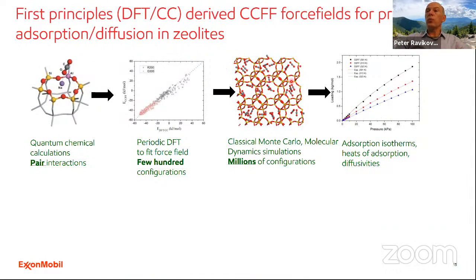As I mentioned before, the quality of the force field is the most important for all the simulations, adsorption or diffusion. One of the approaches we've been taking, in collaboration with the group of David Sholl at Georgia Tech, is to develop force fields based on first principle calculations without resorting to fitting to experimental measurements. In order to do that, we start with DFT calculations, where we perform periodic DFT calculations on a periodic cell of a crystalline material and create the energy grid.